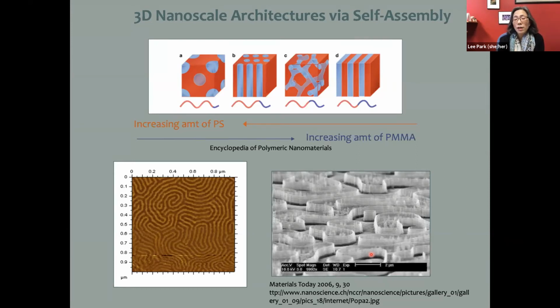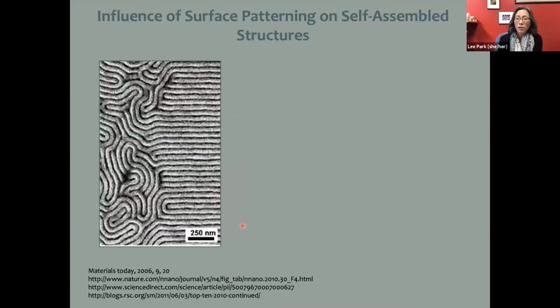So that's pretty amazing. Now you might look at this structure and say, well, there is some regularity to this structure, but perhaps for some of the kinds of things that you want, this isn't regular enough. So this is where we can bring in these ideas of the surface patterning that I was talking about before. That is, you can take a surface and chemically pattern the surface using some of the methods that I described before. And here's what you might get. So this is a surface where this part on the right was patterned in some way and the part on the left wasn't. And then a polymer film of the type on the previous slide is cast onto that and allowed to organize itself. And what you can see is clearly on the pattern side, the polymers have organized themselves into very regular stripes. And on the other side that hasn't been patterned, you get the pattern that I was showing you before.